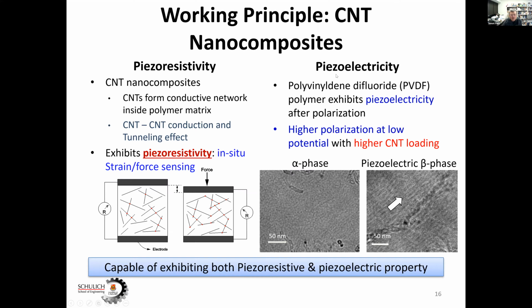Piezoelectric is a sort of different phenomenon. We are using a polymer called polyvinylidene difluoride. Usually it's in the alpha phase, sort of a random orientation. And when you apply pulling, these fibers can be oriented with the pulling direction, okay, and exhibit piezoelectric properties. When you apply load, you have electrons popping out, or the current pops out, or vice versa.